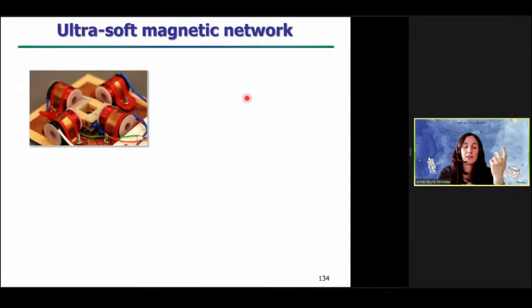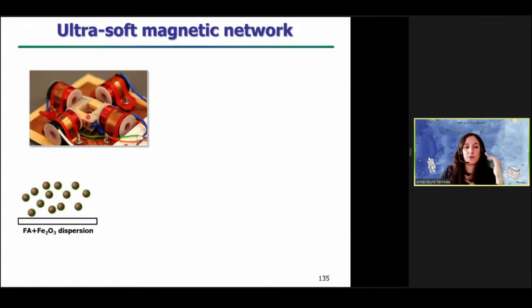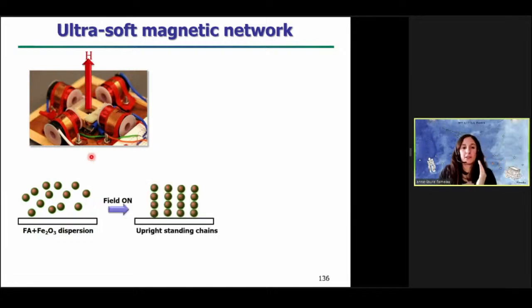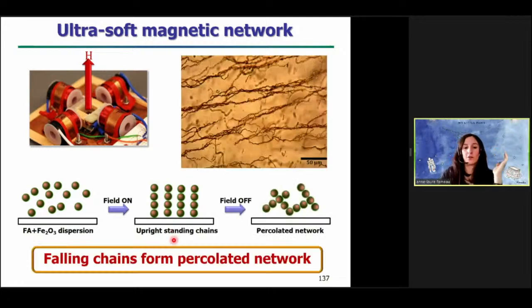So another responsive soft material that we can design from these filaments is an ultra soft magnetic network. To design this kind of network, we just added another electromagnet at the bottom of our setup, as you can see here. We put on the top of this magnet the dispersion of iron oxide nanoparticles and fatty acid soap. We just turn on the magnetic field in this direction. You obtain the formation of upright standing chains. You turn off the magnetic field. Due to their weight, the chains just fall down. And when they touch each other, they stick to each other and form a very nice percolated soft network, as you can see here.